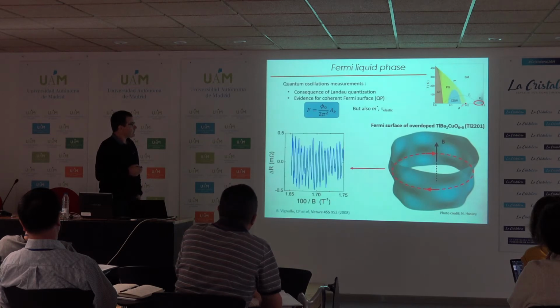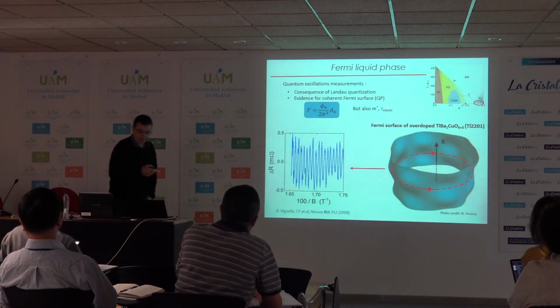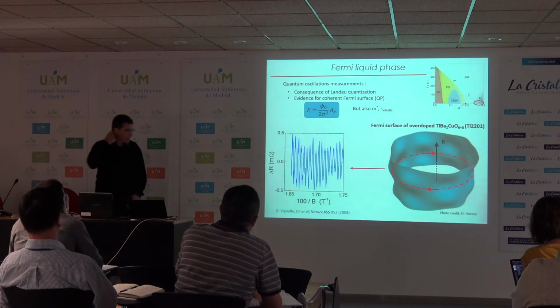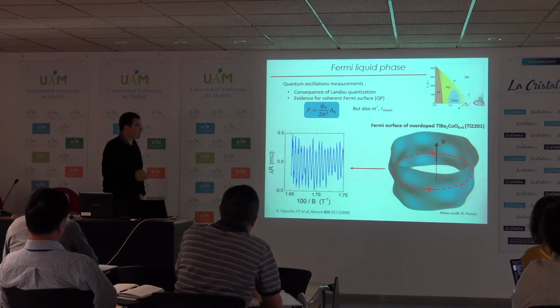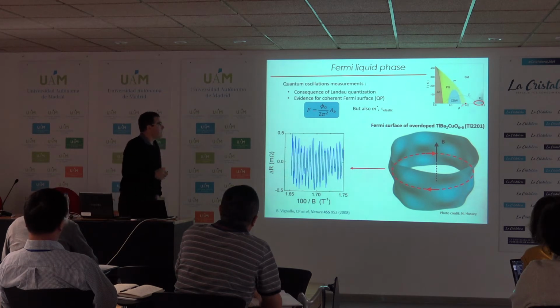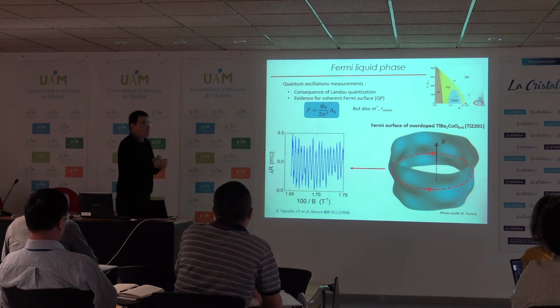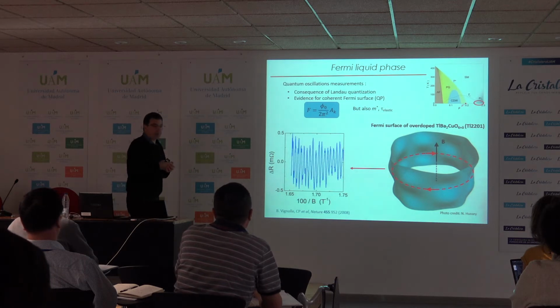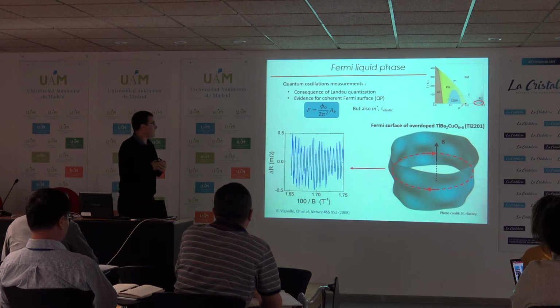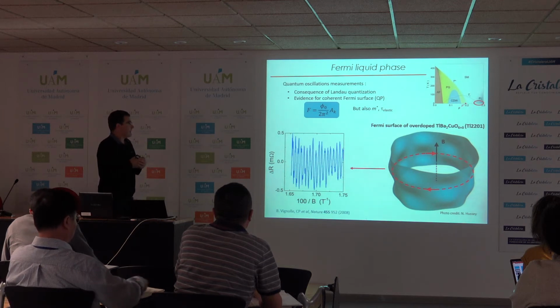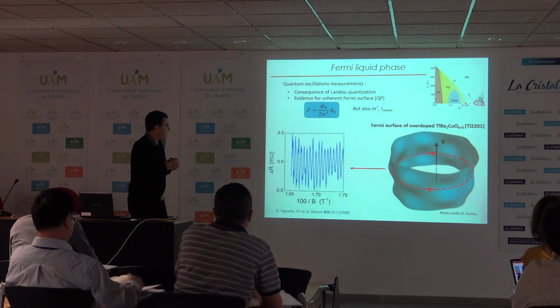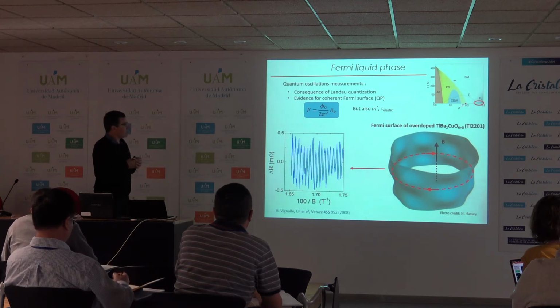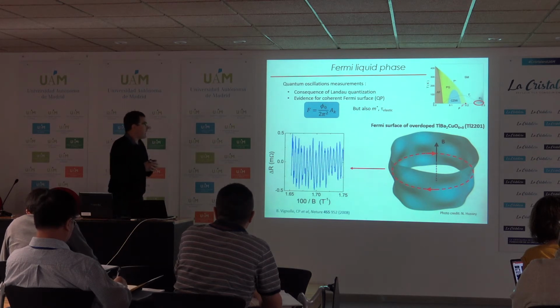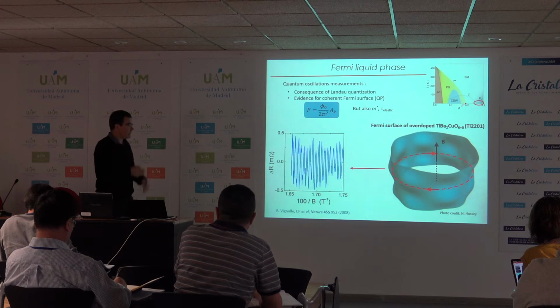In collaboration with the group of Nigel Hussey and Anthony Carrington, we performed back in 2008 some quantum oscillations in this strongly overdoped thallium-2201 compound. I would like to recall that quantum oscillations are a consequence of Landau quantization of electrons in the magnetic field. It's a very powerful technique when you are able to observe them, because the frequency of the oscillation, which is periodic in 1/B, is directly related to the extremal area of the cyclotron orbit perpendicular to the magnetic field.